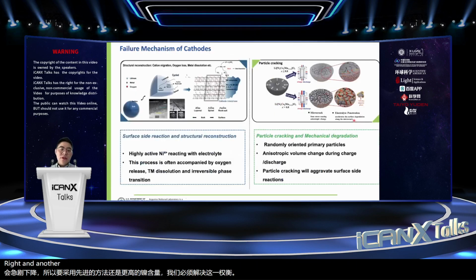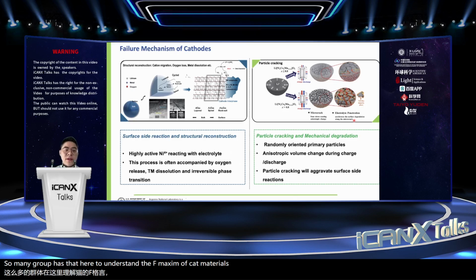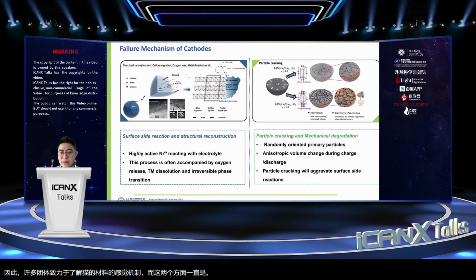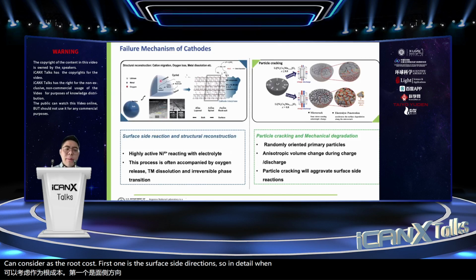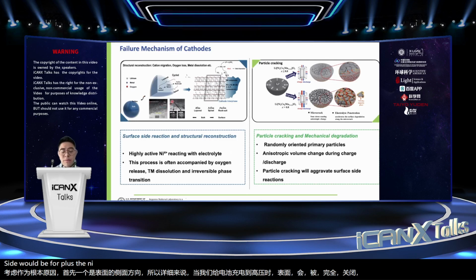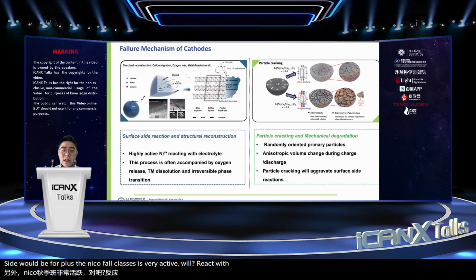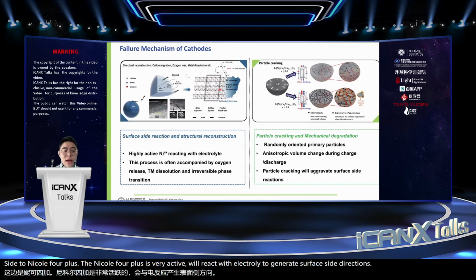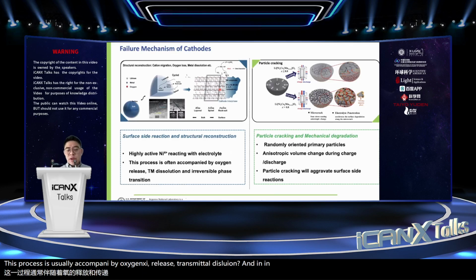And another challenge is we still cannot completely understand why this battery failed this fast. So many groups have dedicated themselves to understanding the failure mechanism of cathode materials, and these two aspects have been considered as the root cause. The first one is the surface side reactions. In detail, when we charge the battery to high voltage, the surface will be fully oxidized to nickel 4+. The nickel 4+ is very active and will react with the electrolyte to generate surface side reactions. This process is usually accompanied by oxygen release, transition metal dissolution, and irreversible phase transitions.